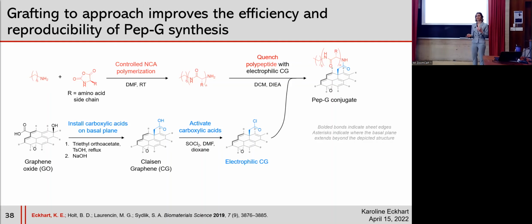So we switched to a grafting-to approach. And this is where we polymerize the NCA in a separate flask, initiated with a known amount of primary amine initiator to create our polypeptide with this active amine end group. And then in a separate flask, we convert graphene oxide to Claisen graphene, which is essentially installing carboxylic acids on the basal plane to replace some of these primary alcohols on graphene oxide. And then we can activate the carboxylic acids to form acid chlorides and use this electrophilic Claisen graphene to quench the amine end group of the peptide to form this covalent PepG conjugate.